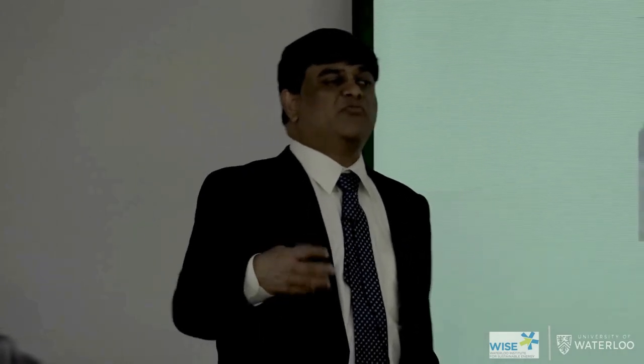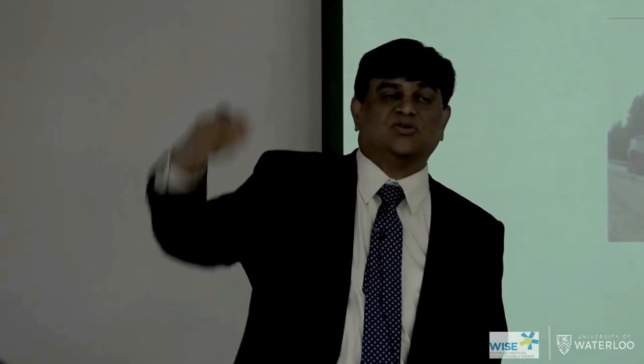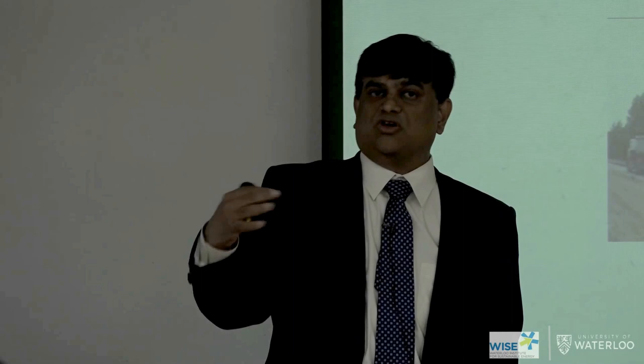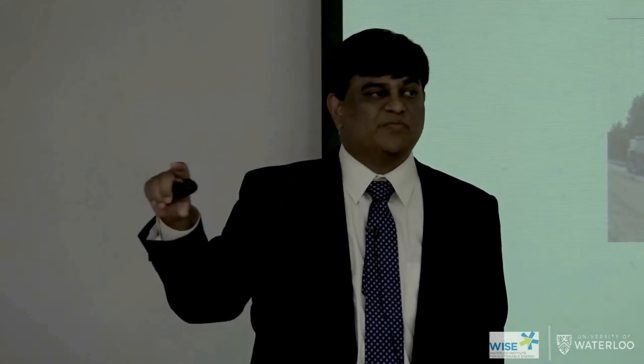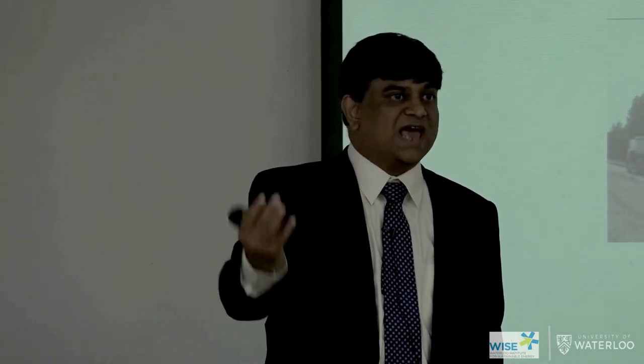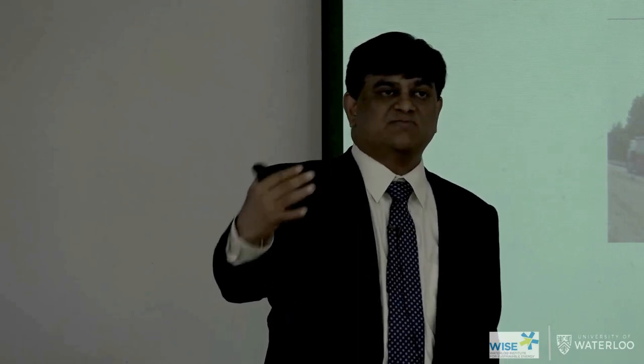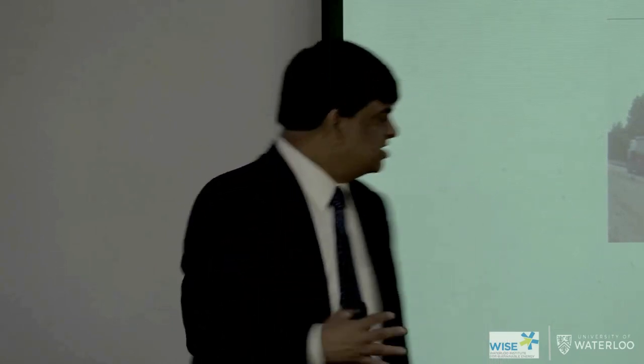Because, in one of our studies, we actually showed you can go up to 45 to 50% without compromising the quality. But for a lot of states, they restrict the amount of usage, okay? I think with time, they will probably increase the percentage threshold. The more you use, hopefully without affecting the base material performance, which you have to investigate in a lab to see that the properties of the base material satisfy what you're looking for, then you could increase this, okay?